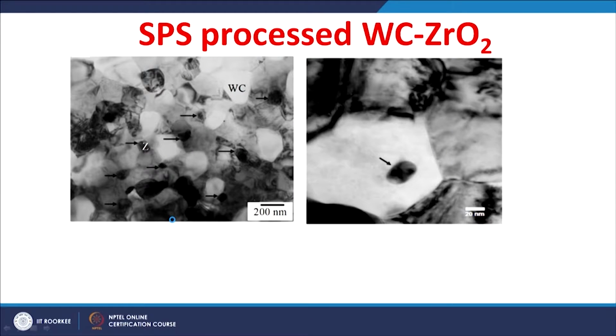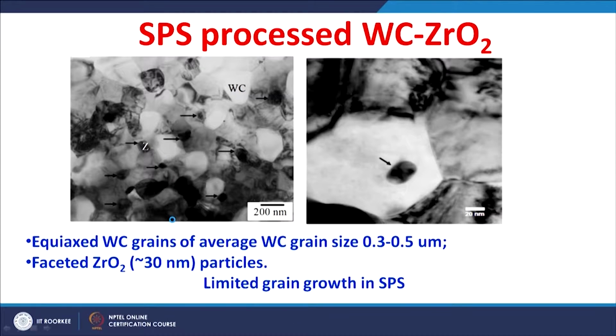The spark plasma sintered tungsten carbide zirconia ceramics showed a microstructure of equiaxed tungsten carbide grains, with zirconia particles along the grain boundaries as well as inside the tungsten carbide grains. The equiaxed tungsten carbide grains have an average grain size of around 0.3 to 0.5 micrometer, whereas the zirconia particles are still in the nano region, at around 30 nanometers, considering the initial particle size of around 0.2 micrometer for the tungsten carbide and around 27 nanometers for the zirconia. So this sintering technique is efficient in giving a dense tungsten carbide zirconia ceramic with nano zirconia particles distributed in the tungsten carbide grain structure.